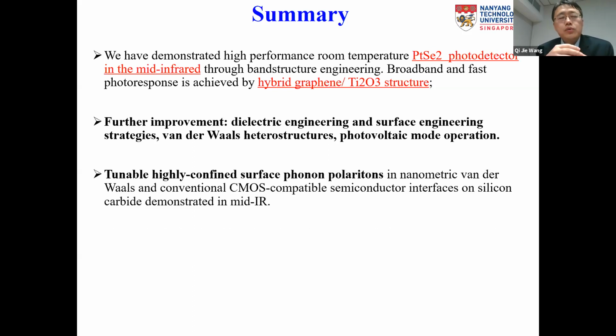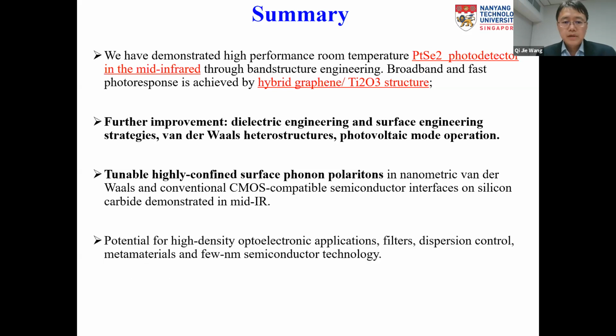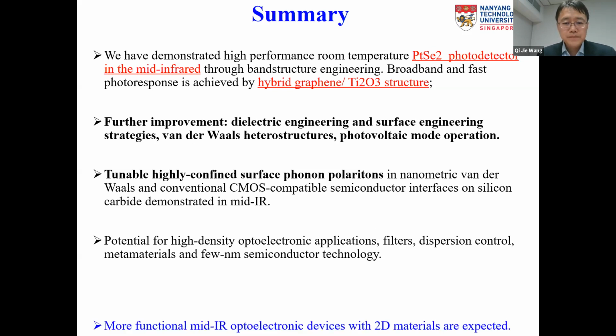We also show you that by using just a very simple three-layer structure, using 2D material as a dielectric layer, we can achieve highly confined phonon-polaritons, with ultra high confinement, up to 100 times or even more, and also demonstrated in the silicon-based CMOS compatible platform. And such a device has the potential for high density optoelectronic applications.